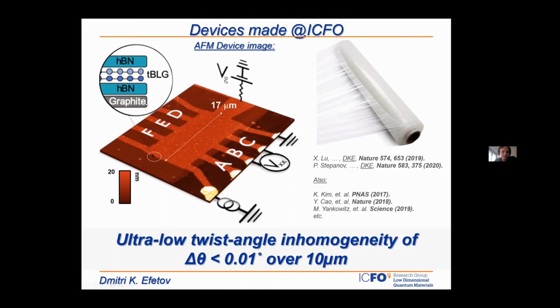Basically, what we can do with this graphite are many things, but first and foremost, we can just apply a voltage to this graphite. And via the capacitance between the graphite and the twisted bilayer graphene, we can tune the carrier concentration in the twisted bilayer. The capacitance is strong enough that we can really empty and completely fill these flat Moiré bands.